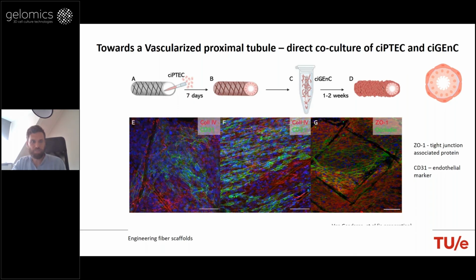So to do that, we looked typically at seeding the endothelial cells at the outer part and the kidney cells at the inner part. And basically what you see here was that we were able to create a monolayer of both cell types using the same scaffolds as a template. And we look at endothelial marker like the CD31 that was highly expressed in the seeded constructs, and you see here by staining in green.